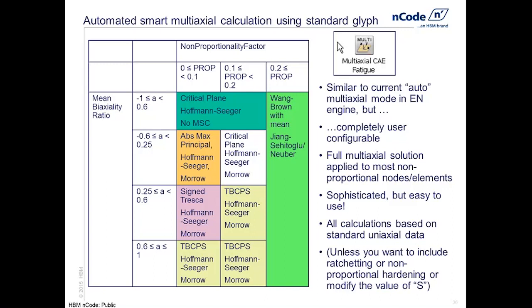But one thing you should avoid doing is applying time history compression on this last step, because remember that the plasticity model and the Wang-Brown calculation, the stress-strain response and the damage, is path dependent. So if you do peak valley slicing, you'll change the loading path.